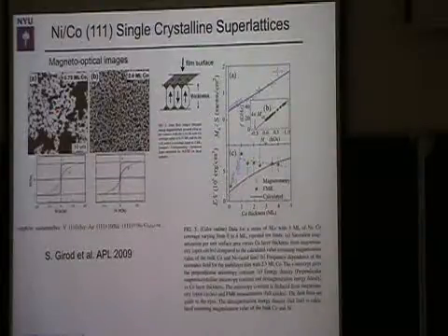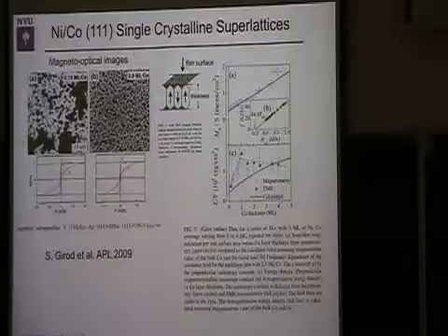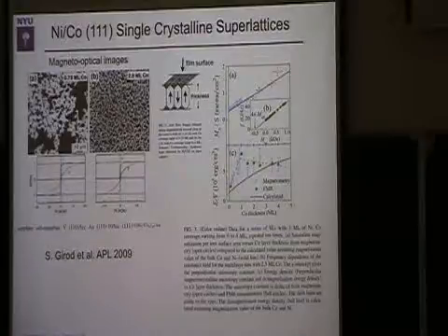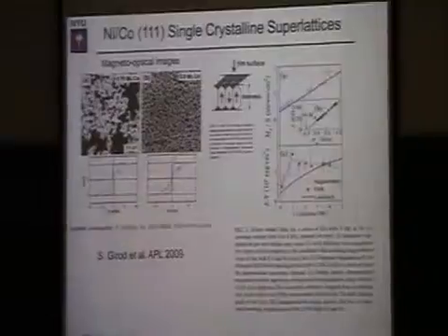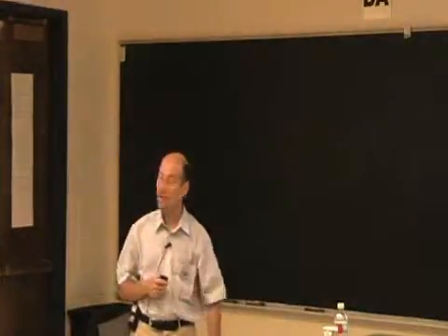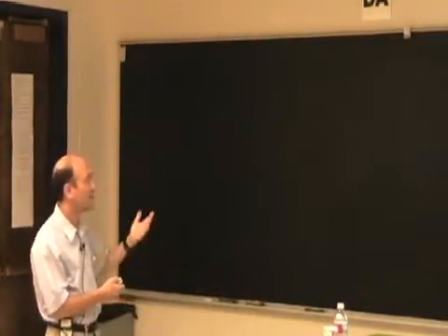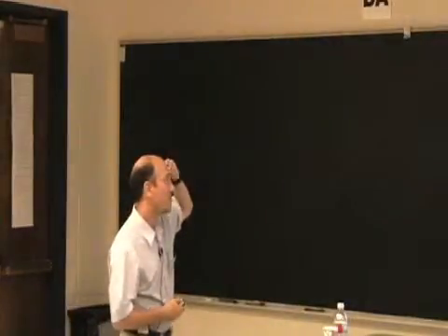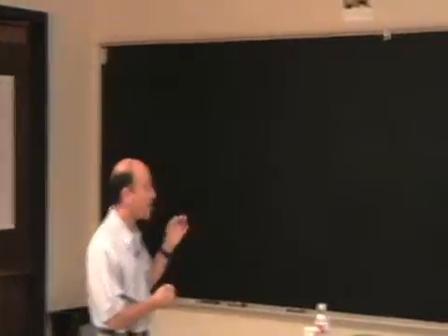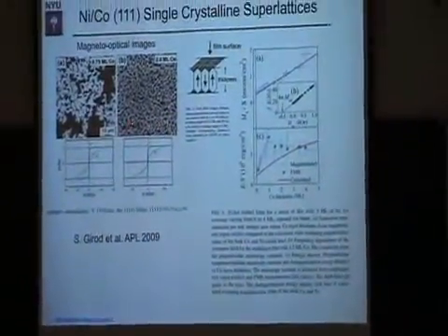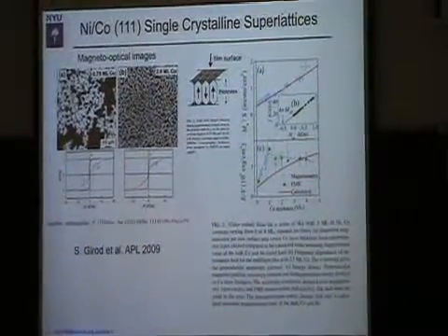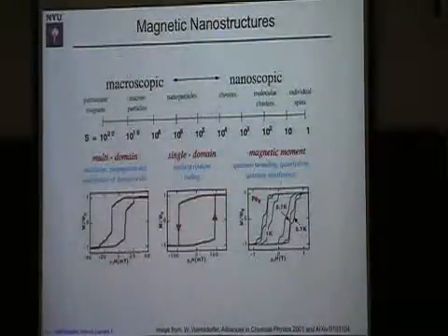There's been a great deal of study of these kinds of structures and domain movements, understanding the domains as interfaces moving in the medium. These objects are like the vortices in a superconductor. They can be pinned on certain types of defects, and they move in some landscape that's determined by how the properties of the material vary. We published a paper on these kinds of materials recently. Our interest is in trying to make very stable, very small structures. So we're starting with films like this and patterning them down in size to try to make very small, single domain magnetic particles.